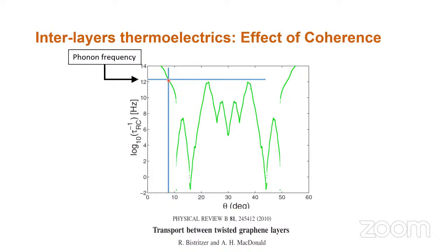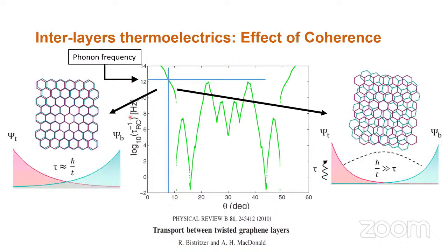become similar. So it means essentially that when the angle between the two layers is smaller than 5 degrees, then the hopping rate is larger, and it's the electron hopping that becomes more efficient to make the electrons go from one layer to the other. And the standard Landauer-Büttiker formula for the diffusion thermal power, the Mott formula, is good enough to explain the thermoelectricity.